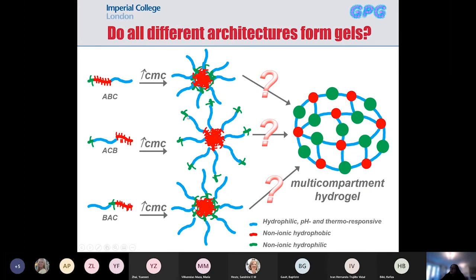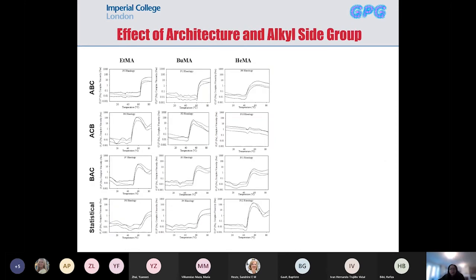Well, in this case, both hydrophilic chains are in the corona of the micelle, and these two micelles are actually of higher size than this one. So the question was, will they all form thermogels or not? And they do, but they're not all forming stable thermogels, and they don't all have the sol-gel transition that we want. So we want a very clear solution to gel transition, so sol-gel transition, like this one.